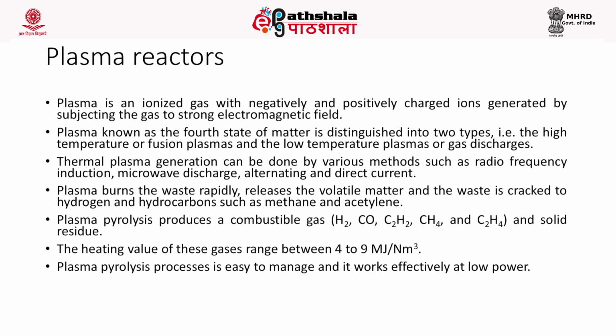Now, thermal plasma generation can be done by various methods such as radio frequency induction, microwave discharge, or alternating and direct current. Plasma burns the waste and releases the volatile matter, and the waste will be cracked into hydrogen and hydrocarbons such as methane and acetylene. Plasma pyrolysis also produces combustible gases like hydrogen, carbon monoxide, and methane, and a solid residue is also produced. The heating value of the gases will range from 4 to 9 megajoules. Also, the process is very easy to manage and it works effectively at low power.